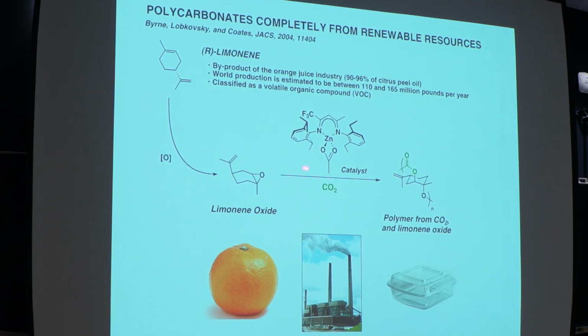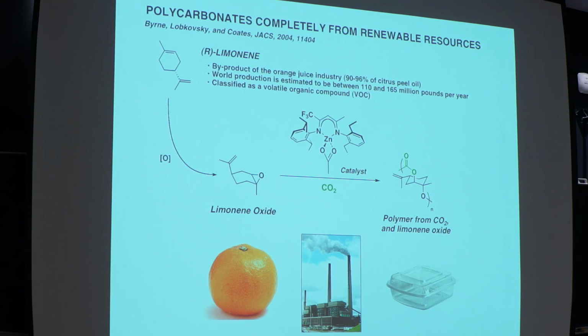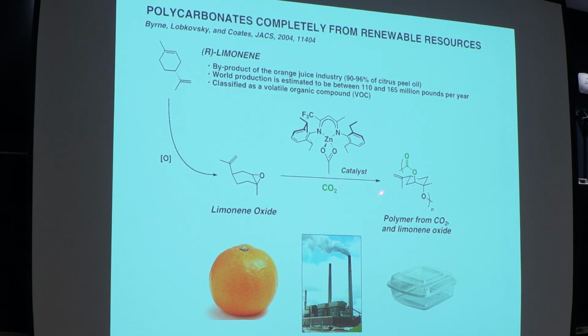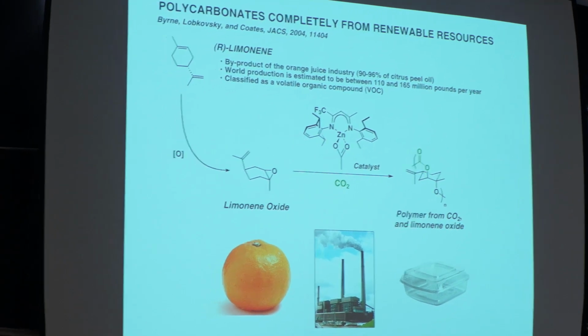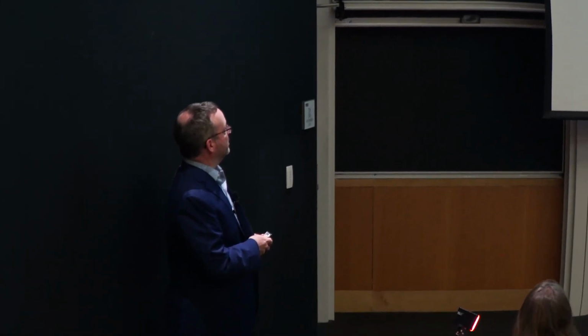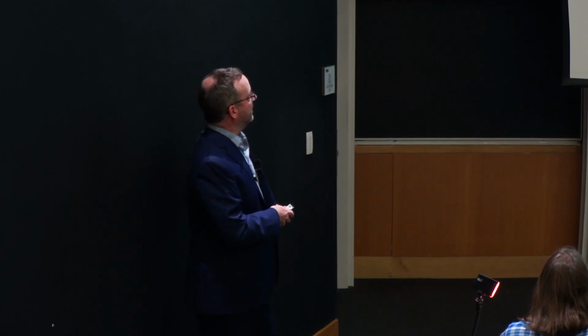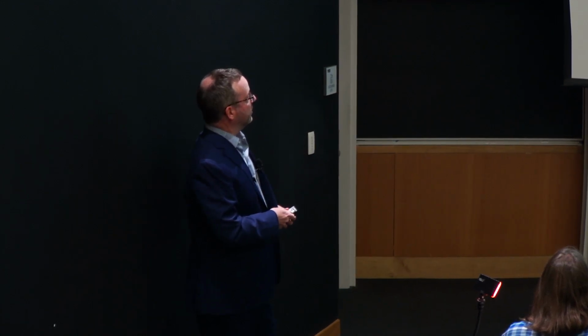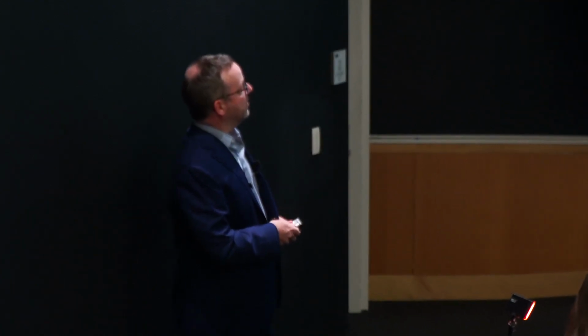And again, I would love to give you a half an hour lecture on how we came up with this catalyst that is, to my knowledge, the most active and the very first catalyst that was able to polymerize limonene oxide and CO2. But instead of talking about the catalyst, there are some interesting features of the stereochemistry of this polymer. Given that oranges have a stereocenter here, and so you build in the stereocenter here, and then the epoxidation, you can control that to give either cis or trans. And then when you do the ring opening of the epoxide, you invert the stereocenter at the site of attack. And so this polymer is perfectly stereoregular. All the stereocenters are dictated by that original stereocenter up here on the limonene molecule.